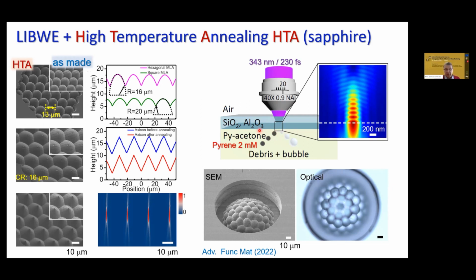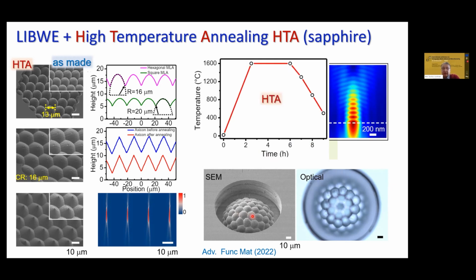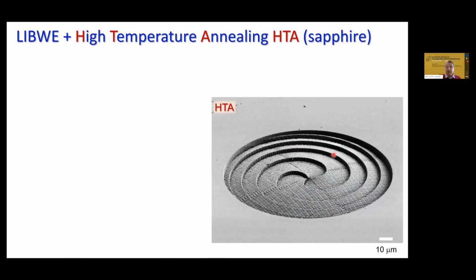This is the way you can sculpt nicely 3D surfaces and optical elements. But ablation is never perfect in terms of optical performance. It has some roughness, and you need to deal with it. For glasses, it would be high temperature annealing, which will make all surfaces spherical. And this is not ideal. Sometimes we want surfaces which are not spherical, for example, an aspherical lens. And here, with the crystal, is something different. Once we fabricate, we can apply high temperature annealing, and the temperature is really high, but it is not high enough to melt sapphire. Sapphire melts at still 500 centigrade higher. So after fabrication, this annealing is making very smooth surfaces.